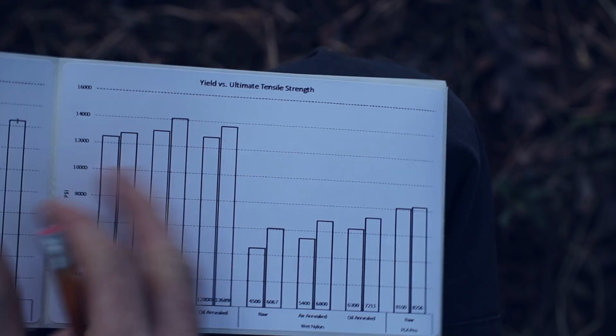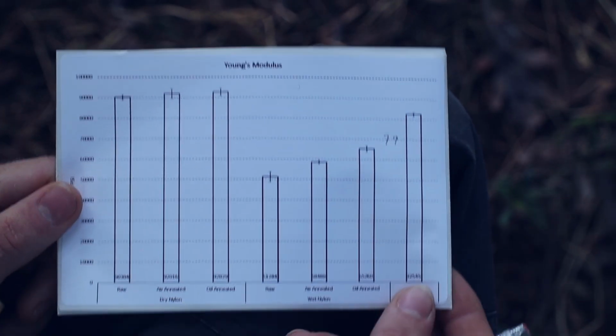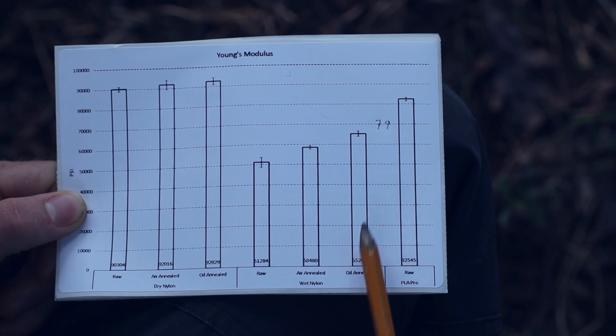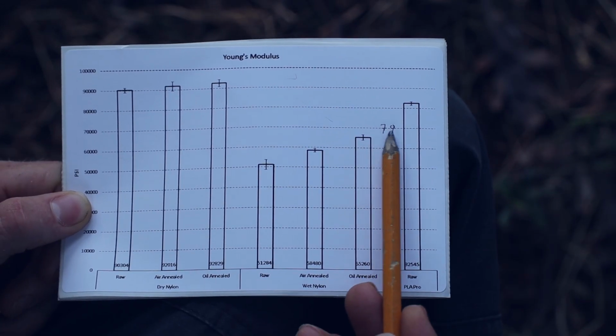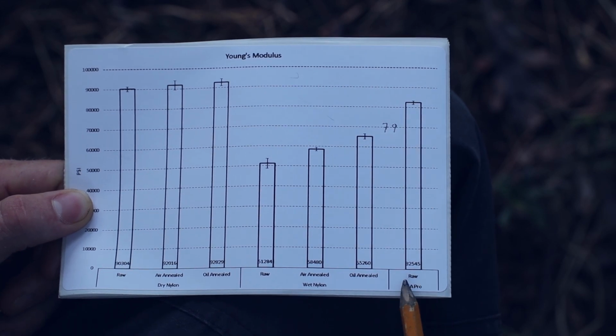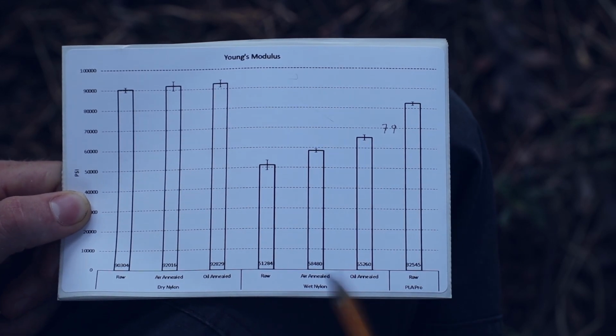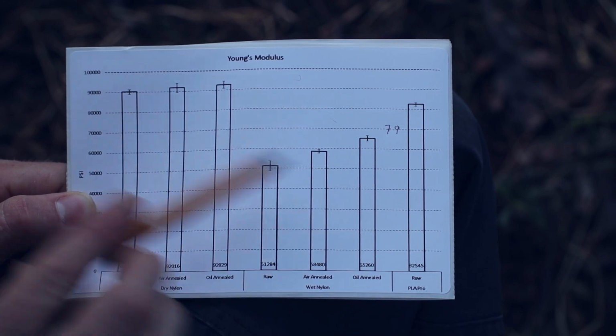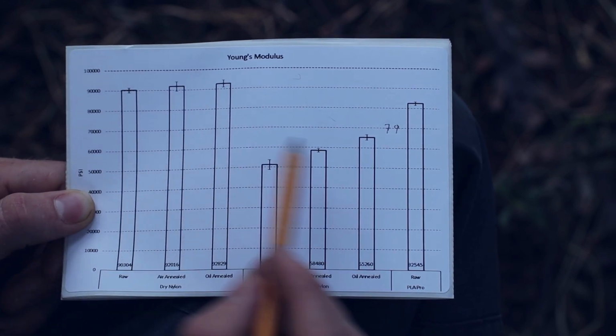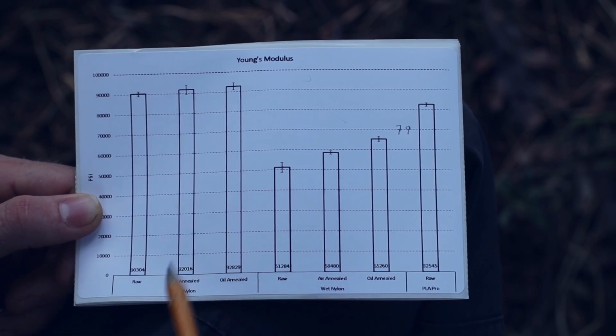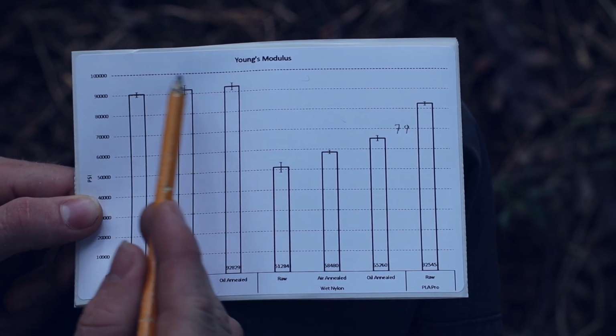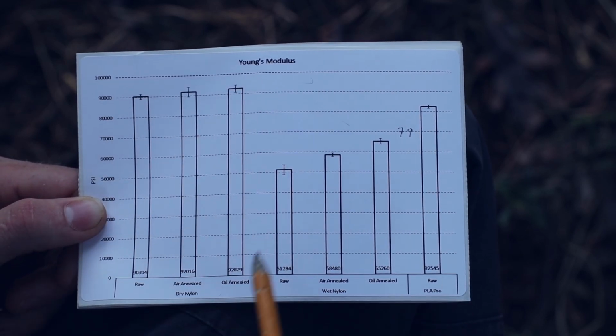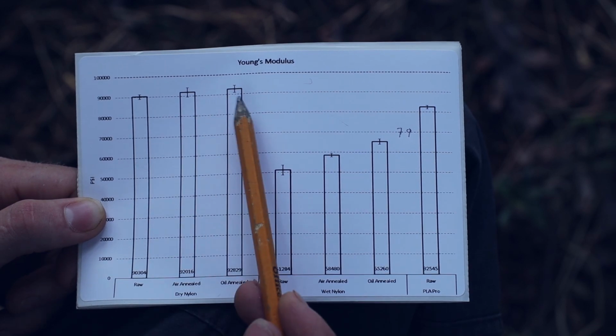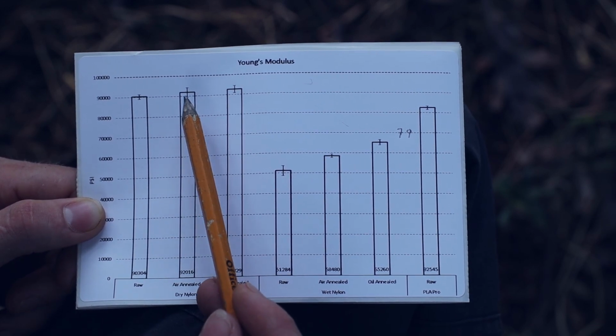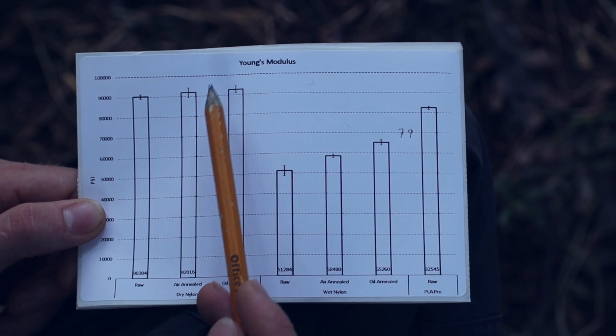Now this moves us right into our next graph, which is the Young's modulus. Here you can see that the oil annealed nylon is only 79% of the Polymaker PLA Pro, which is significantly less than it was with the tensile strength. Looking at our Young's modulus, everything looks pretty similar here, except the dry nylons are very, very similar. There are very few discrepancies, and the oil annealed actually comes out very slightly stiffer than the air annealed, even though it was slightly weaker on the ultimate tensile strength.